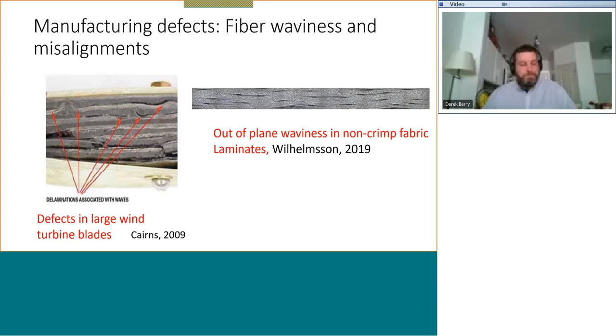Here again, from a Sandia report, for thick composites, typically for wind turbine applications, but this will also be the case for tidal turbine blades. They are going to be relatively thick, which means there are going to be thermal gradients, and they are going to produce, through shrinkage of the polymer, waviness. The left picture shows a severe waviness that has already caused delamination before you put that in service. On the right is an example I have taken from Sweden, where for the Volvo company they are developing composites for jet engines and such. There you see shaded areas showing a waviness between the layers, although these are more process-controlled examples.